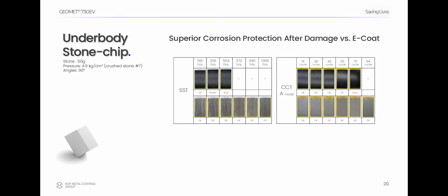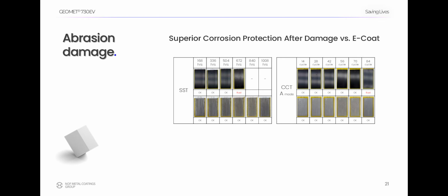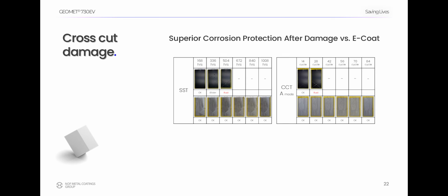This is important for future battery pack design. If the battery case becomes more exposed to the underbody area, stone chip resistance will become more important. We also tested other damage conditions such as abrasion and cut areas. The results showed the same direction. GeoMet 730EV maintained better corrosion protection than E-coat.